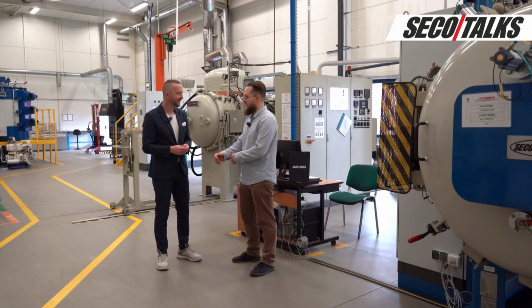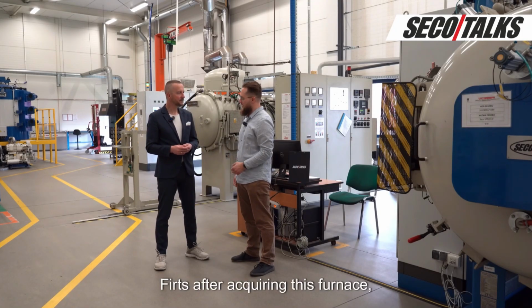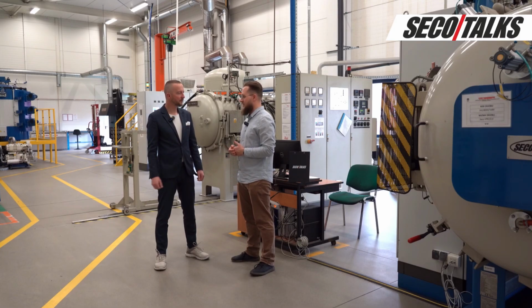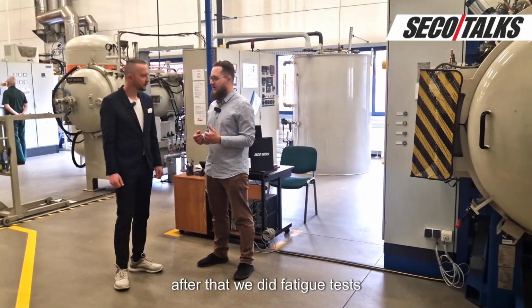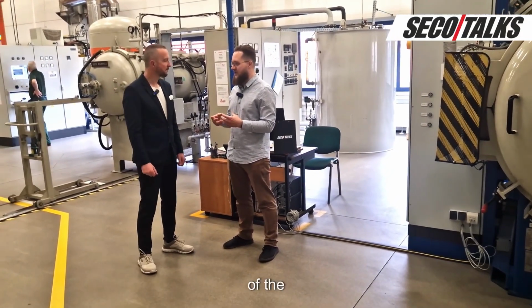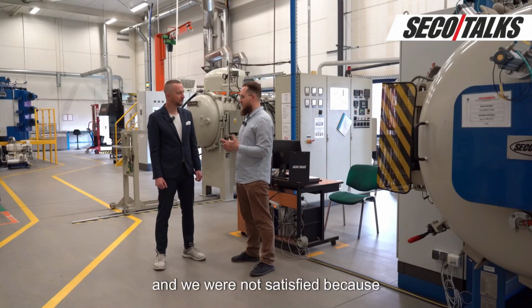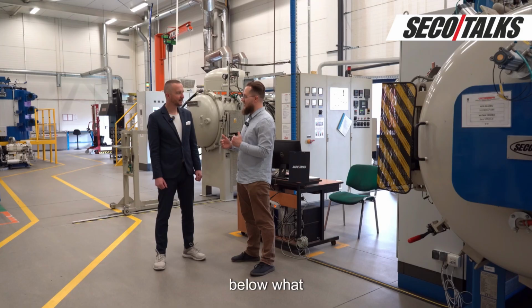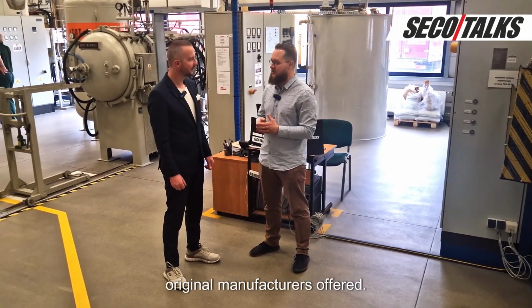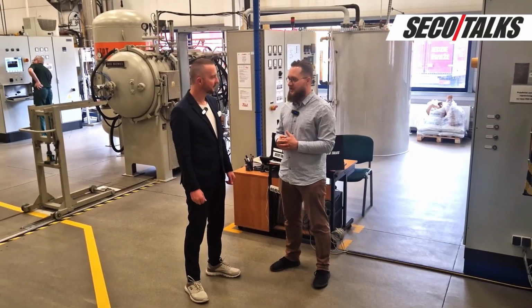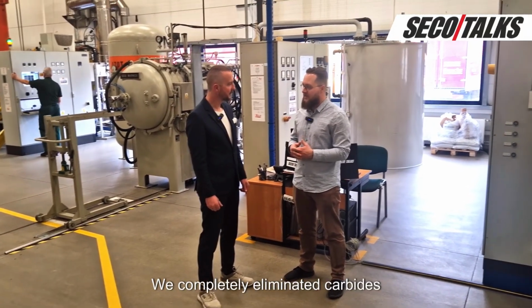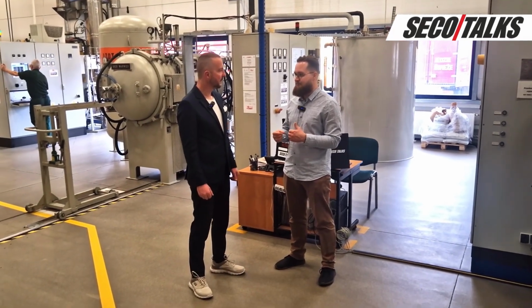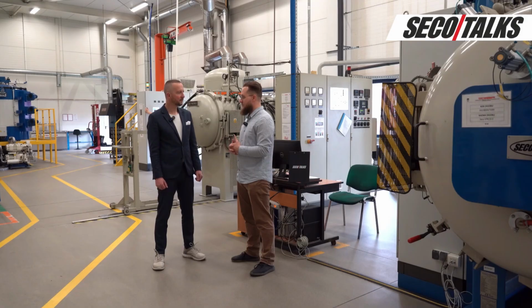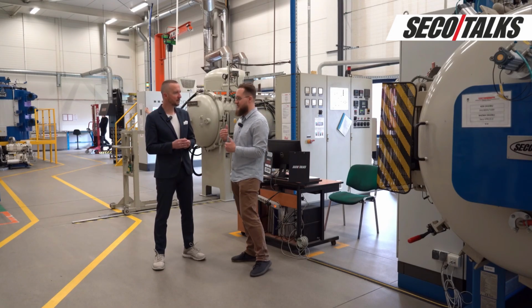Yes, first, after acquiring this furnace, we started with some initial parameters for the case depth and hardness profile. And after that, we did fatigue tests of the finished element. And we were not satisfied because it was below what the original manufacturers offered. After that, we changed the parameters. We completely eliminated carbides from the carburized case. And the fatigue test results are much improved.